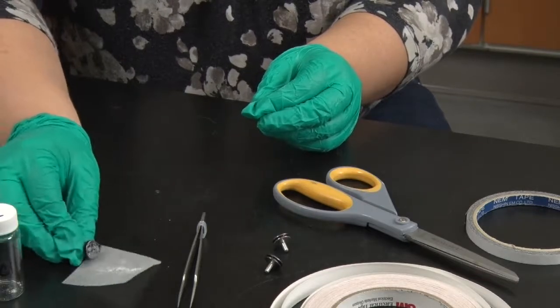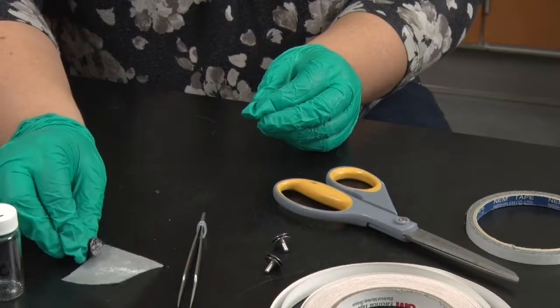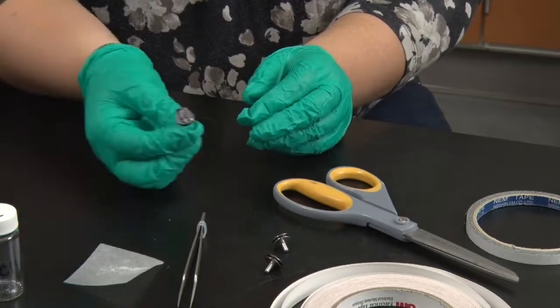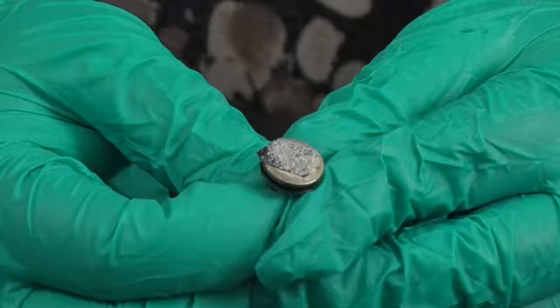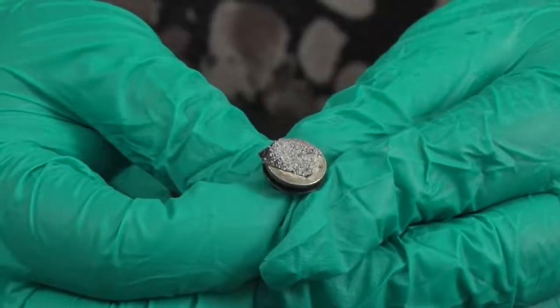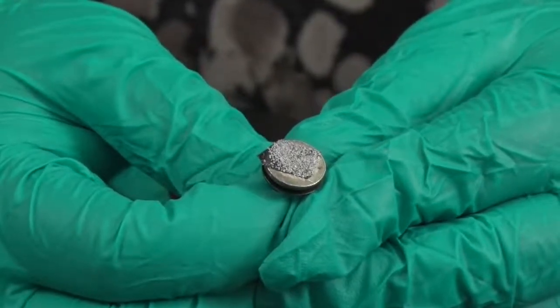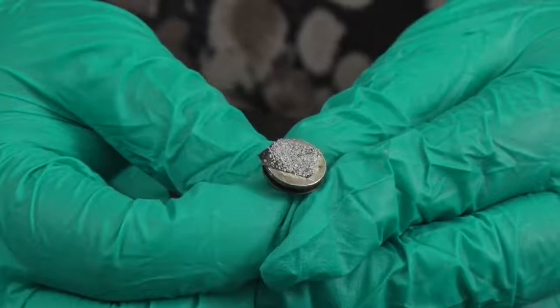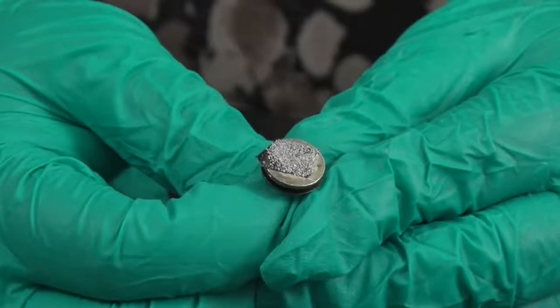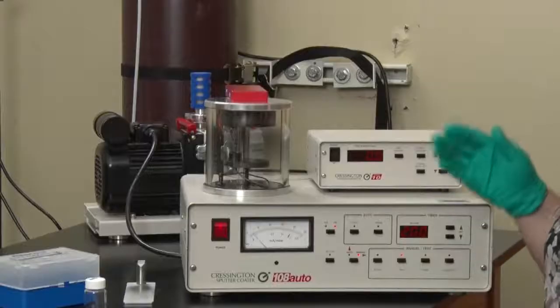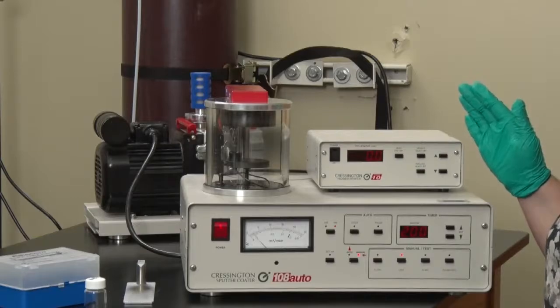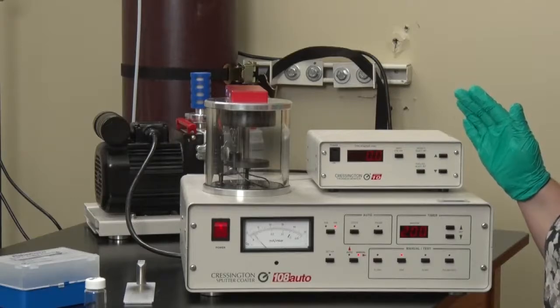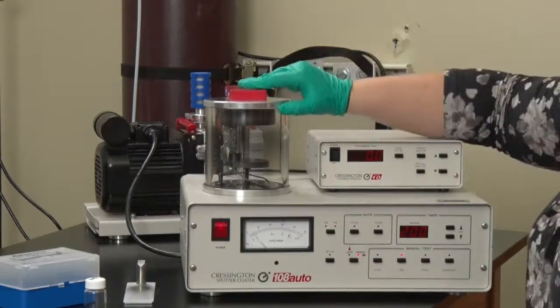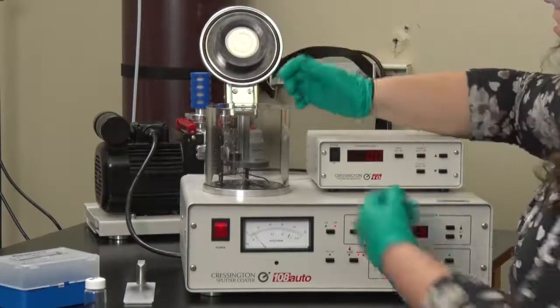By gently tapping the sample stub on the table, I can remove any excess salt that is not well attached. Samples that are not conductive need to be coated with a conductive coating for traditional SEM imaging in order to prevent charging problems. Our lab uses a sputter coater to deposit a thin layer of gold palladium, but some labs use a carbon coating instead. I'll place the sample in the sputter coater.